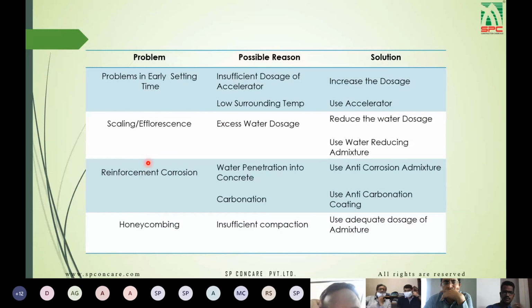Next is reinforcement corrosion. Why does reinforcement corrosion occur? Due to water penetration into the concrete, or due to carbonation of the concrete, the reinforcement corrosion may happen. So use anti-corrosion admixture, or the anti-carbonation coating. The last problem is honeycombing. Honeycombing may occur due to insufficient compaction, when bleeding or segregation happens. So use the adequate dosage of the admixture. But if honeycombing occurs after the construction, you can use our product, that is Duracon 49, to repair it.